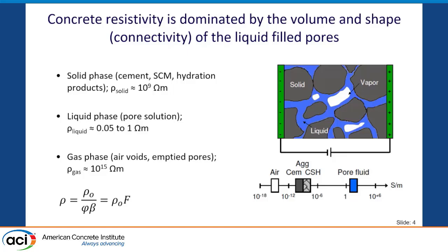As such, the resistivity of concrete is a function of how resistive your pore solution is, and then how much of that pore solution you have, or how connected that pore solution phase is, which is your porosity and beta. So if you take that resistivity and divide it by the resistivity of your pore solution, you get that formation factor, which is a true measure of transport properties, diffusion coefficient, permeability, if you will, of your concrete.